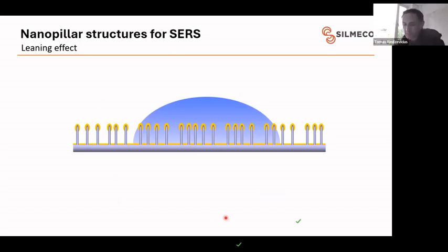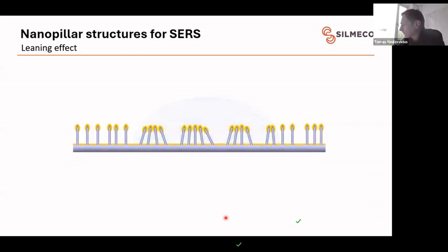And now I would like to turn to the second interesting part of these substrates. So first is that it's easy to fabricate. The second is that they have this property of what we call the leaning effect: when you deposit a droplet on the surface and the droplet dries, capillary forces pull the pillars together and they create these small micro clusters. And if you remember from my earlier slides, this is what you would want, to bring particles together to create these hotspots. So this is what we are doing essentially, bringing them all together. So they are nearly touching here. Of course, these are not spheres like in my previous slides, but the essence is the same.